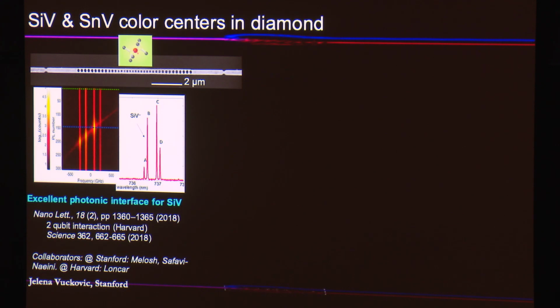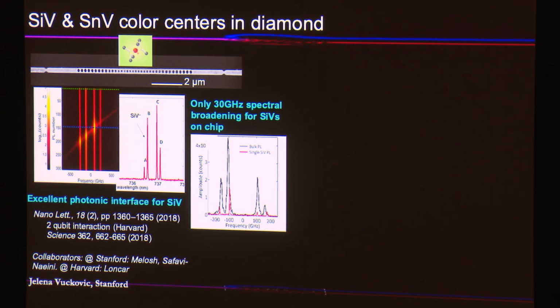So here in one slide, I'll show you where we stand in terms of quality of qubits in diamond, such as silicon and tin vacancy color centers. Over the past couple of years, we've shown that we have an excellent photonic interface for silicon vacancy color center in diamond. This work was done in collaboration with the group of Marko Lončar at Harvard, and there was also related work at Harvard where it was shown that there is an excellent photonic interface for silicon vacancy in a diamond cavity, and even larger cooperativity than what we saw at 4 Kelvin temperature. So that's all great. That's one desired parameter for the system.